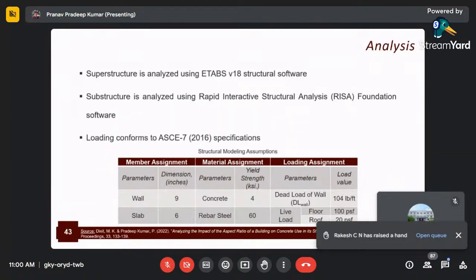So we assumed a 9-inch thick drywall and a 6-inch thick concrete floor slab. The concrete strength was taken as 4 KSI, or roughly 28 to 30 MPa. And the rebar steel that we considered here was 60 KSI, that's roughly 450 MPa. And all the other loading parameters here conform to the ACI.